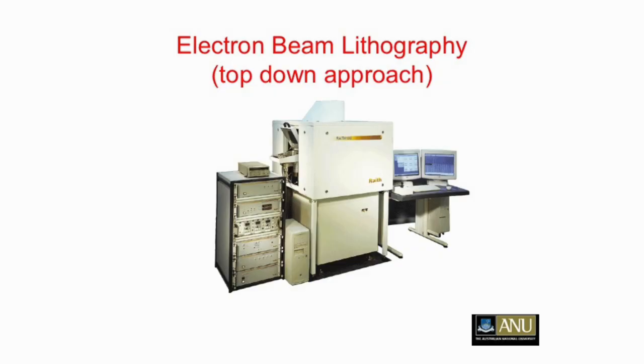In fact, we do the top-down approach as well. This is an electron beam lithography system in our laboratory, and it's a $2 million machine, and we can really write the patterns using electron beams, and we can create features as small as 20 nanometers or so. In fact, we are now trying to establish the future facilities whenever the NCRIS program gives us money, to be able to even go as small as 2 to 3 nanometers by using the top-down processes, because the properties change quite significantly when you go to those dimensions.